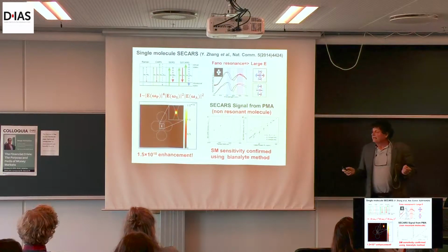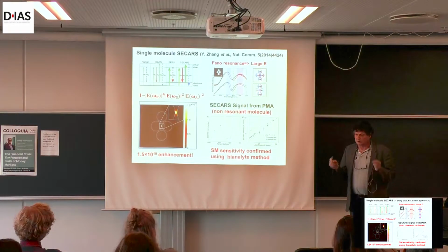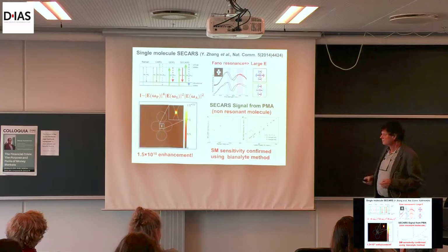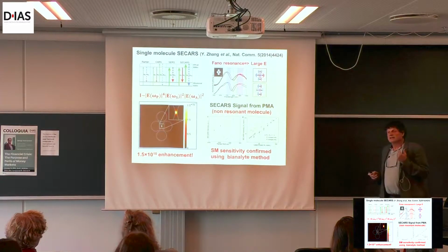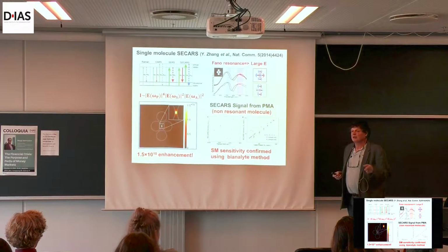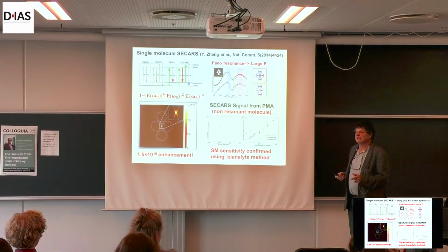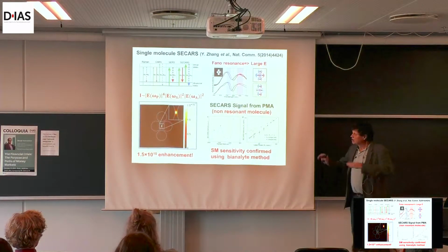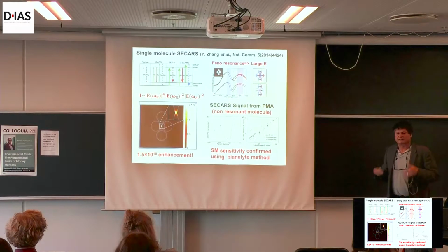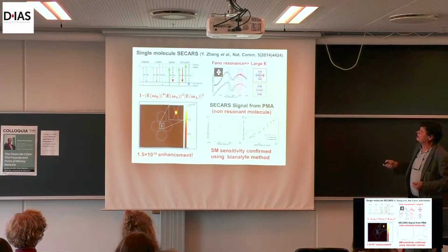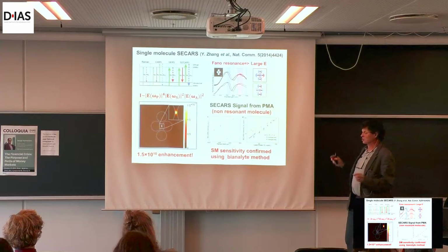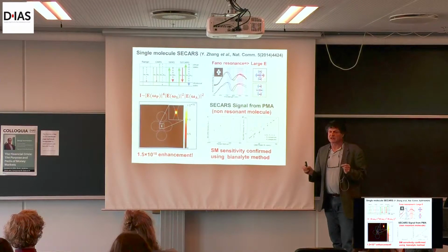Basically, if you take a mixture of two molecules, A and B, and you pour that over the structure, then if you are reporting spectroscopy from a single molecule, you will see either no signal, or signal A, or signal B. You will never see A and B. There's more mathematics to this, and you do this with controlled variations. It's a statistical approach, but that is how we were able to prove that we had single molecule spectroscopy here. We never saw the simultaneous appearance of spectral lines A and B.